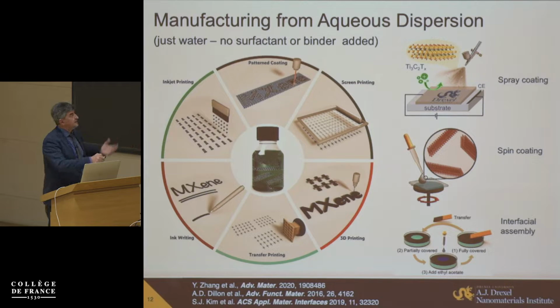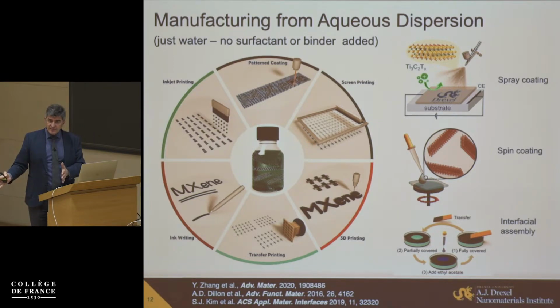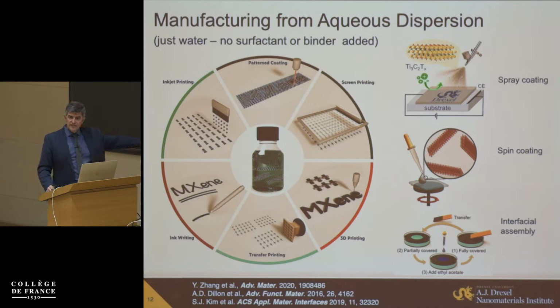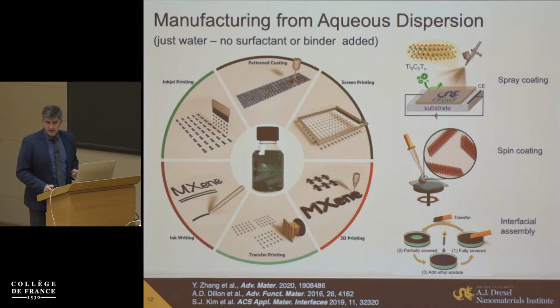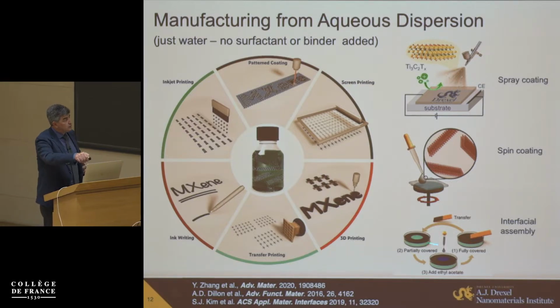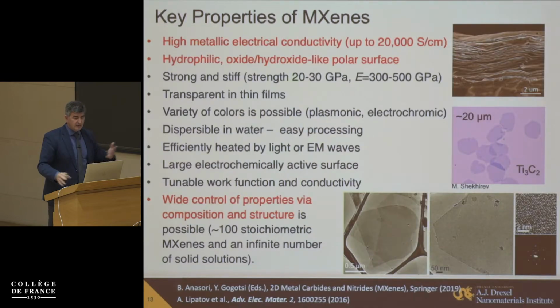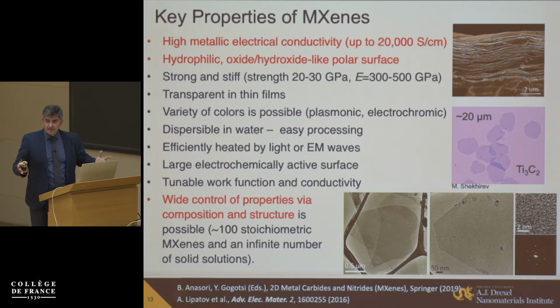You can print it by using any known printing technique. You can do spin coating, spray coating, doctor blading. If concentration is high, you can get liquid crystalline behavior. It helps to align flakes nicely, even in a thick film, if you do, for example, doctor blading here. But you can also assemble monolayer films at the interfaces here. So again, it's nothing new in processing, but again, the advantage is here.